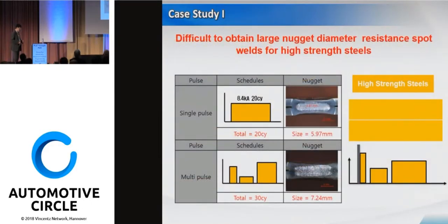So this is some of our research. There are some difficulties in obtaining a large nugget diameter in resistance welding of high strength steels. In single pulse, you can have about a maximum 6 millimeter nugget diameter with a 6 millimeter electrode tip. But we used multi-pulse, 3-pulse, with a high current pre-pulse, an intermediate pulse and a main pulse current. We actually got a nugget diameter of up to 7.24 millimeters using the 6 millimeter electrode tip diameter. So this is the animation.